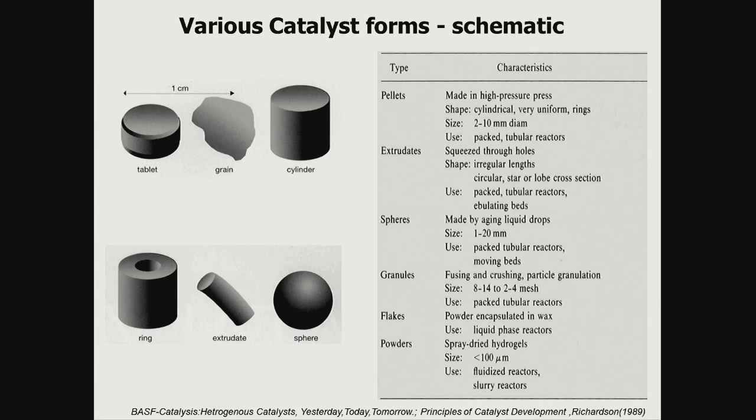This one here is a problem, because it's a tablet. And depending how you make it, you can actually start to anneal the surface, you could blind the surface, so you could end up with this thing having low surface area. But the shift catalyst tended to be a tablet, and it's meant to be dispersed evenly throughout the surface. So it's meant to have a surface area, but it's got a surface area more akin to 50 metres squared per gram.